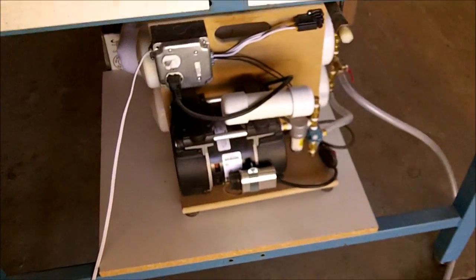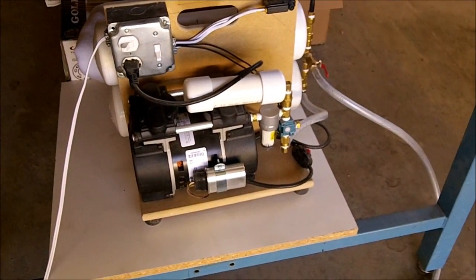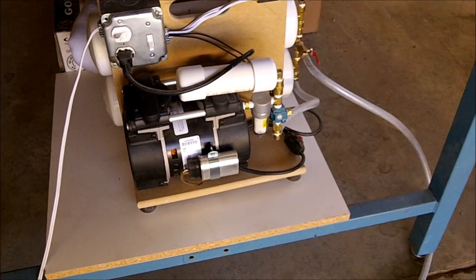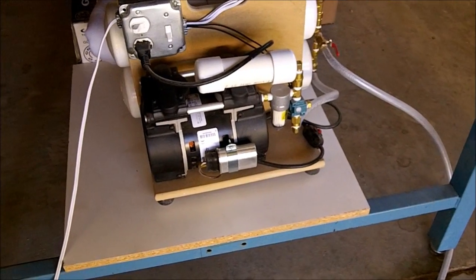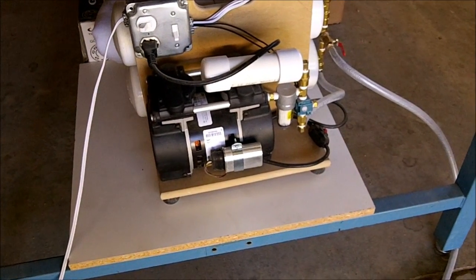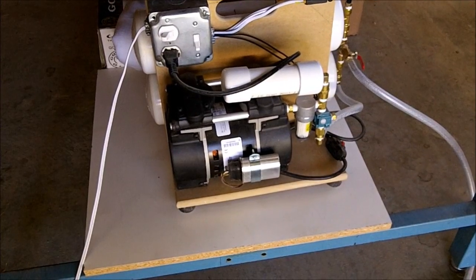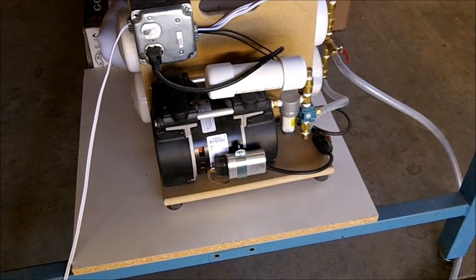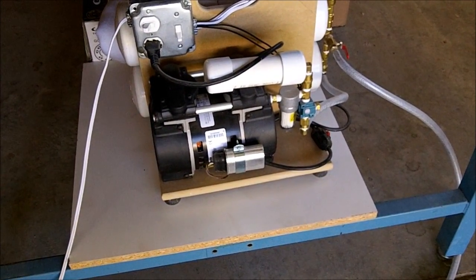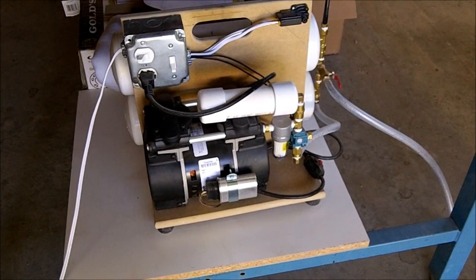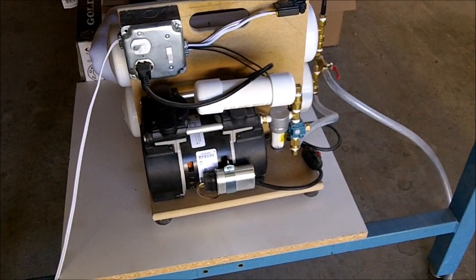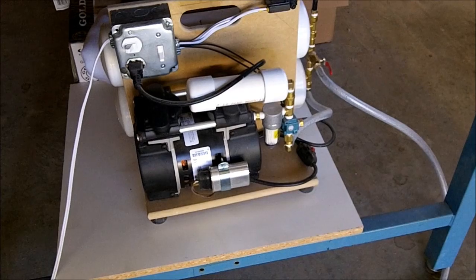I just find that doing two hoses on here helps get a better vacuum. Here's the pump that I'm using. I've got this from Veneer Supplies. It's a great pump. Right now, it's pulling 24 inches of mercury. So, we're good there. It's a good vacuum. Also, this pump doesn't run continuously. It can. But I've got it set up so that when it gets up to a certain point, it shuts off. And then, when the pressure falls below another certain point, it kicks back on.